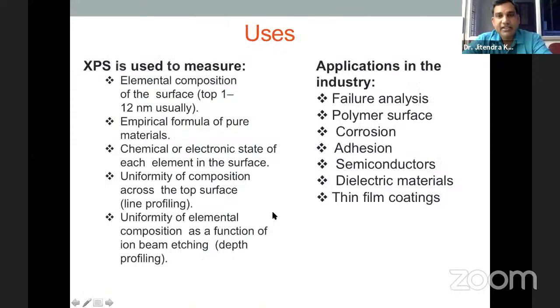So these are the applications in industry: failure analysis, polymer surface, corrosion, adhesion, semiconductor, dielectric material, thin film coating. This XPS is used widely, and it can also be used to measure the elemental composition, even though the surface depth required is 1 to 12 nanometer. So surface preparation is also very important for XPS analysis, and it can give you the chemical or electronic state of each component. So these are the analyses which can be performed using XPS.